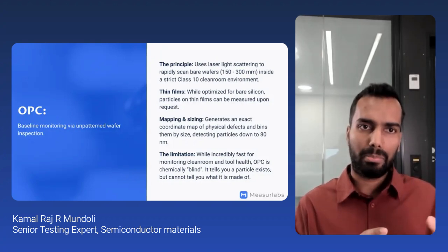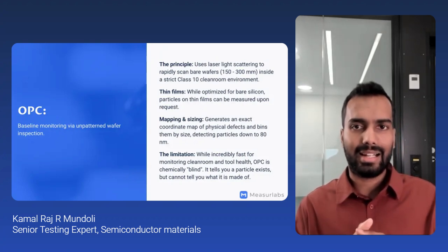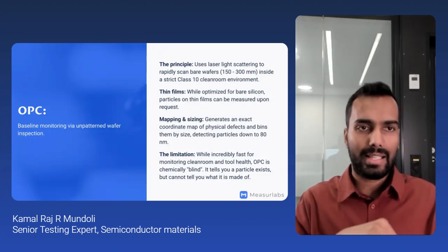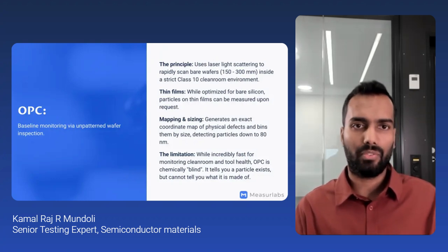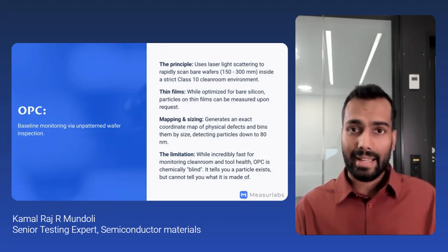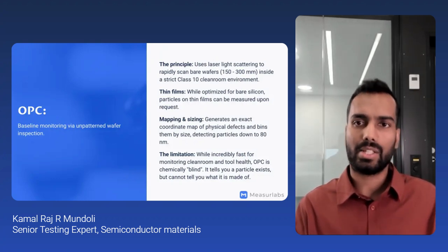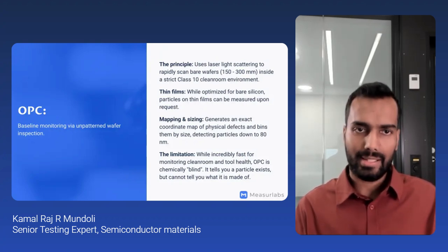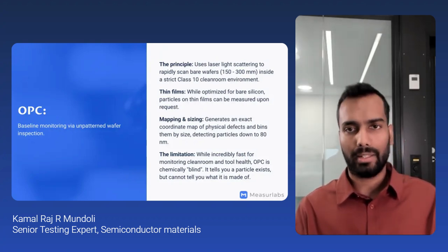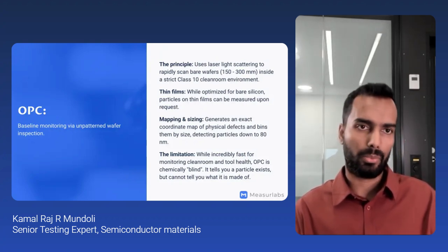The core principle relies on laser light scattering to rapidly scan unpatterned bare wafers ranging from 150 to 300 mm, entirely within a strict Class 10 cleanroom environment. While it is optimized for bare silicon, we can also measure particles on certain thin films upon request.